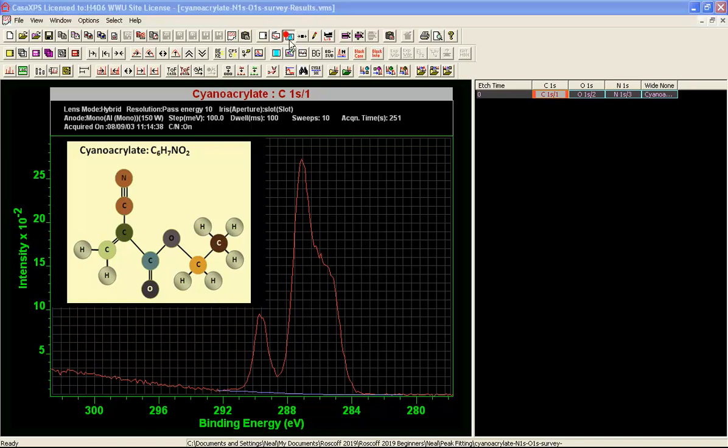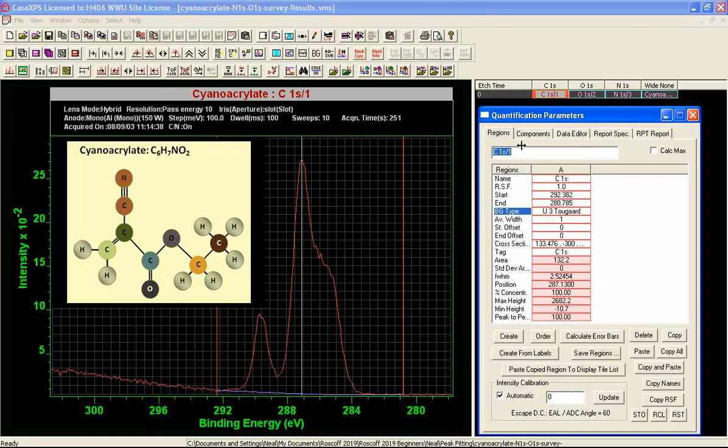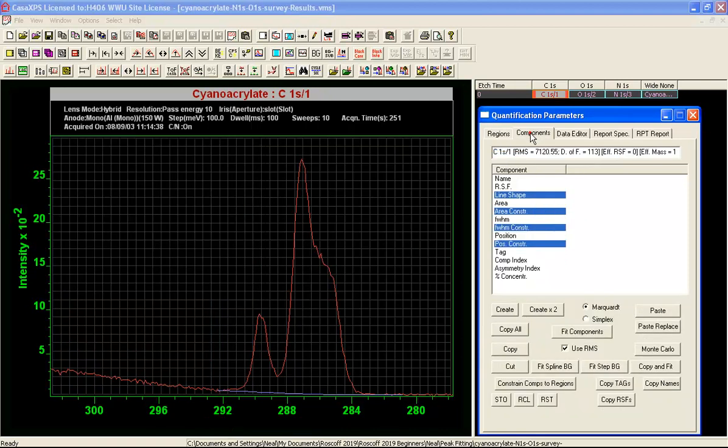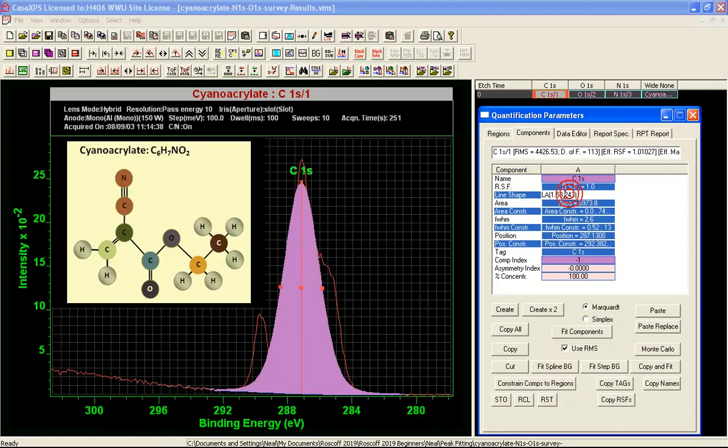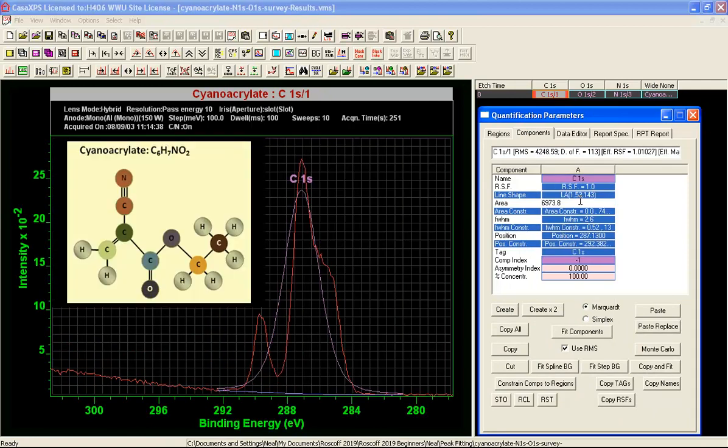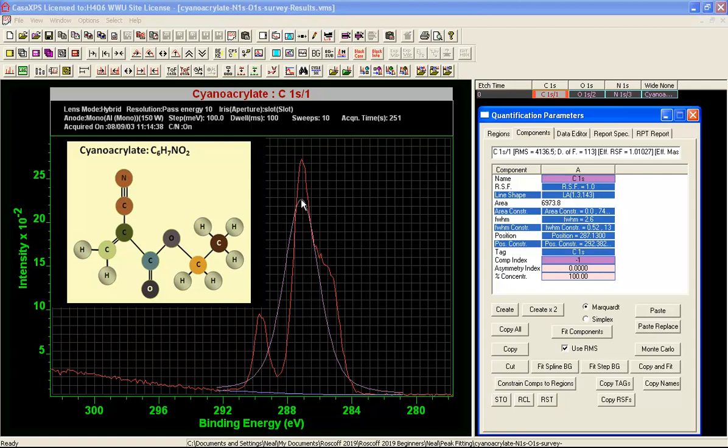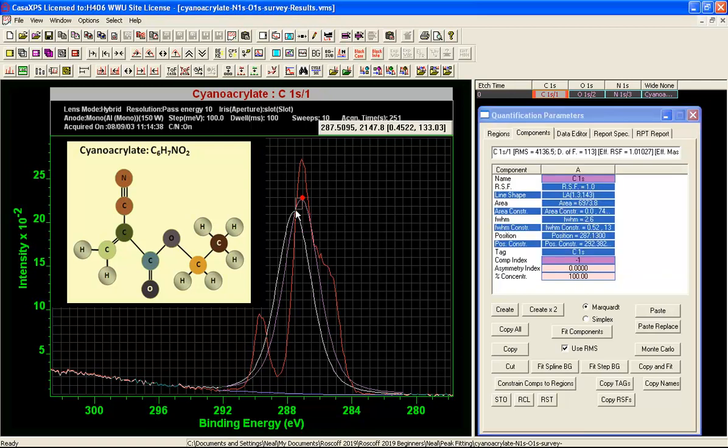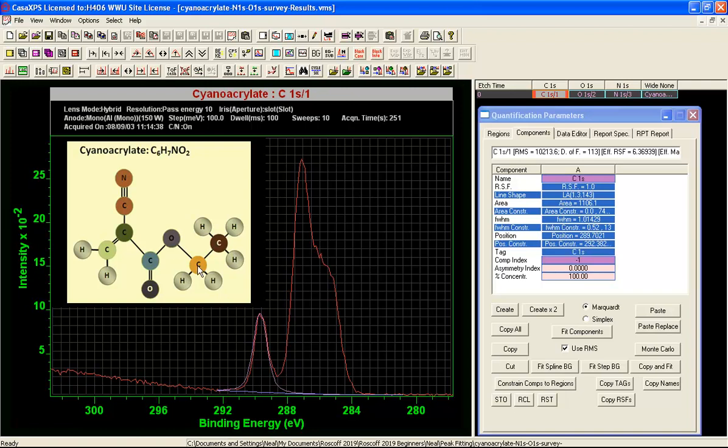So let's add some component peaks. So our background was already prepared on these data when we quantified with respect to these other high resolution spectra we created this region. And if we now add a component peak, let's just reduce the Gaussian contribution and we'll also reduce the deformation of the wings so that we end up with a peak that might be appropriate for this carbon double bonded to oxygen.